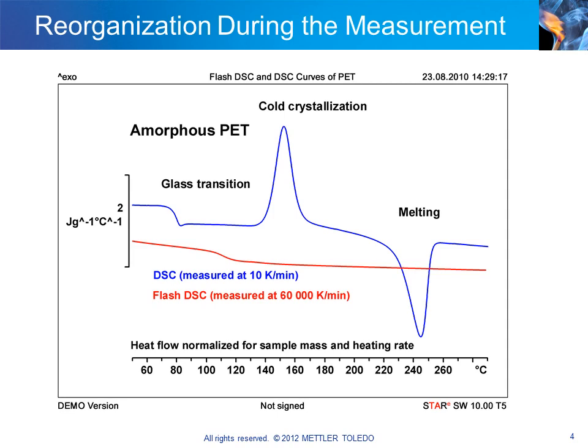Reorganization cannot occur at this extremely high heating rate because not enough time is available. The material is measured in the state it was in before the measurement, or as found. There is no time for any structural changes to occur. We can now draw two important conclusions from this result.